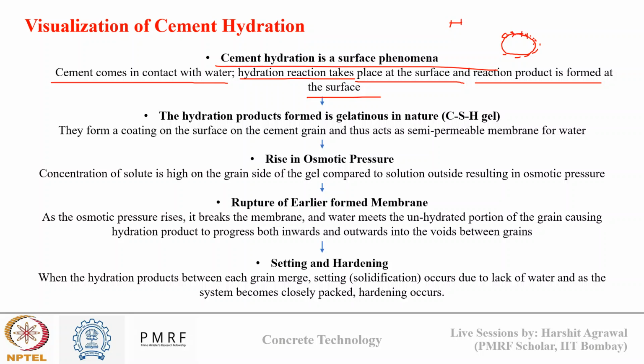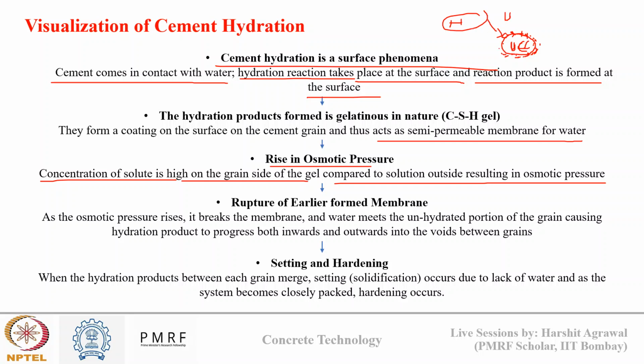This CSH gel will form on the surface of the cement grain, and it will produce a semi-permeable membrane for water. So inside I have unreacted cement, but there is a membrane of CSH that has formed over this cement grain, which will act as a barrier for interaction of water with the unreacted cement inside. Okay, now what happens? This gives rise to osmotic pressure. The concentration of solute is higher inside the cement grain compared to outside. So unreacted cement is very high inside and very low outside, and water is high outside and low inside. So there is a concentration gradient that has developed due to this layer of semi-permeable membrane that has formed over the cement grain.